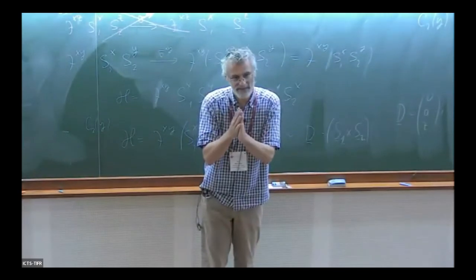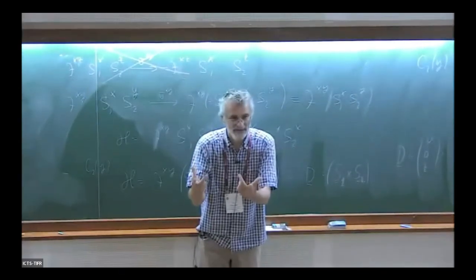Minus epsilon. Okay, so let's stretch this epsilon a little bit. Just a few remarks. What you saw here is that if we have this oxygen not in the center of the bond, but slightly off, then there is a term that appears, which is proportional to S1 cross S2. This term is a triple product. It wants to span a volume with D, S1, S2. They don't want to be in a plane. They want to span a volume if possible.